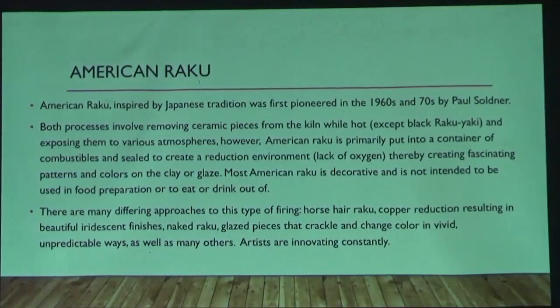So both processes involve removing ceramic pieces from the kiln while hot, and we're talking 1600, 1800 degrees Fahrenheit, about cone 06 to cone 04. And exposing them to different atmospheres, being how much oxygen is in the clay. There are reduction atmospheres where you take away most of the oxygen, and oxidation atmospheres where you pump in a lot of air, and they both give different tones, such as a copper glaze. You've all seen copper oxidize, it turns green or blue-green. So in an oxidation environment, a copper glaze is prone to turning blue-green. In a reduction environment, you steal all the oxygen away from it, and it turns bright red.